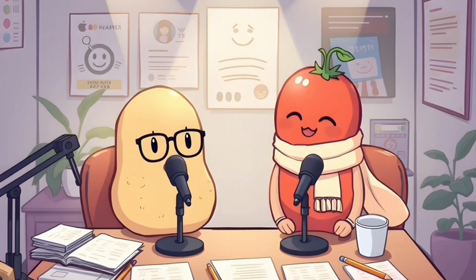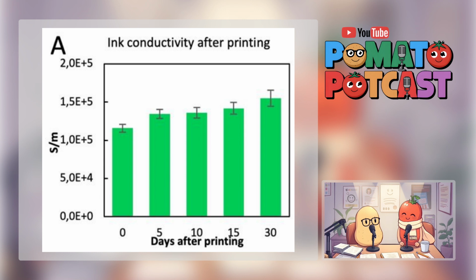Okay, flexible, easy to make at room temp. Sounds great. But let's dig a little deeper. What's the science? Why does this ink perform so well? It's about how those tiny silver flakes pack together inside the polyurethane binder. Interestingly, the conductivity actually increases slightly over the first 30 days or so after printing. It gets better over time. Yeah. It seems to be due to slow water evaporation from the water-based polyurethane. As the last bits of water leave, the silver flakes get packed more densely. Closer together, easier for electricity to flow.